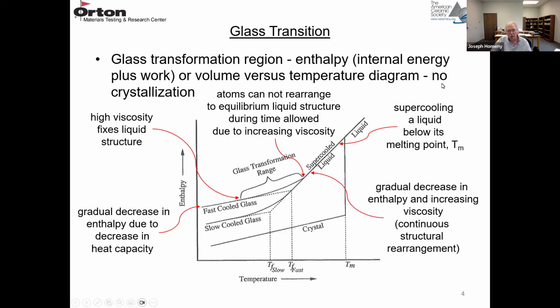And this is what happens when it doesn't crystallize, so no crystallization. So you have a liquid, you reach its melting temperature, so it's supercooled below the melting temperature. It doesn't crystallize, so now you have a gradual decrease in enthalpy or volume with increasing viscosity as the temperature is lowered. So it's not discontinuous, it's a continuous structural rearrangement. Then you reach this point here where it deviates from linear behavior. So the atoms cannot rearrange to equilibrium in the liquid structure because the time allowed is not long enough because the viscosity is increasing. And then finally, you reach this point here where the viscosity is high and now the liquid structure is fixed. So there's no more atomic rearrangement at that point.